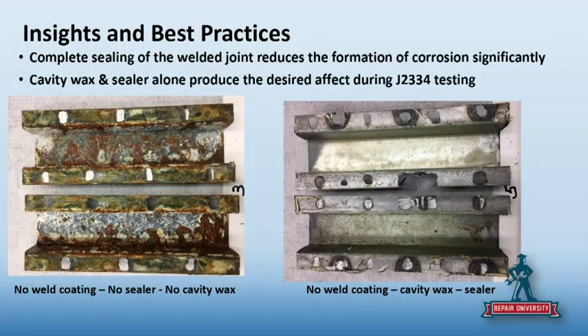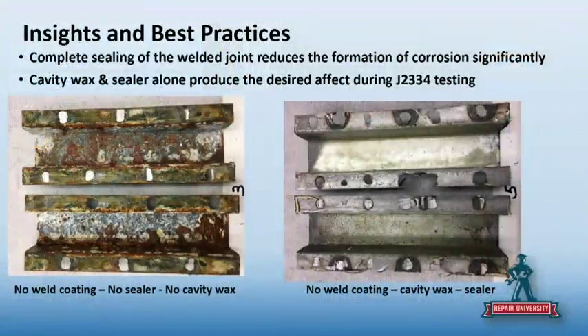And as you can see, stark difference between the one on the left, which has basically nothing in there, and it's badly corroded. The interesting thing about the one on the right is that this is a sample where we did not even use a weld-through primer on the flanges, just left the flanges bare metal. And you can see what an amazing job that cavity wax did of protecting against corrosion. That went through the same exact test in the same salt chamber as the one on the left. And it's a pretty obvious difference. Live on the right, die on the left. That's right. So cavity wax wins the day.